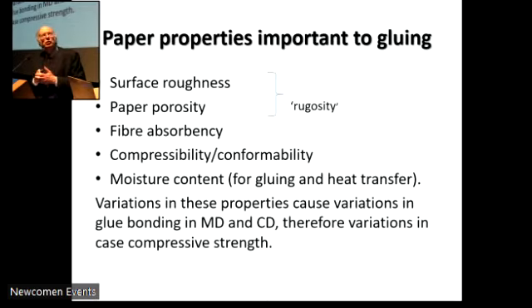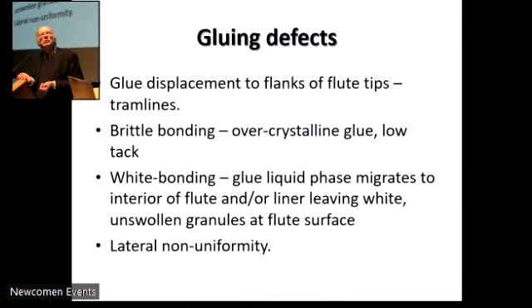And then finally, there's moisture content, not only because of its possible retarding effect on the glue cure, but also because paradoxically, the more moist the paper is within certain limits, the better the heat transfer. And more heat equals more rapid cure. And variation in these paper properties causes problems in glue bond formation in both the machine and the cross direction. And therefore, ultimately, variations in the compressive strength and performance of the case.